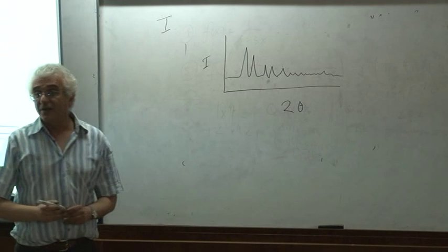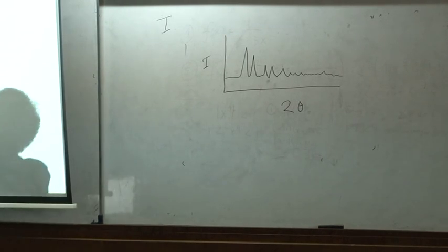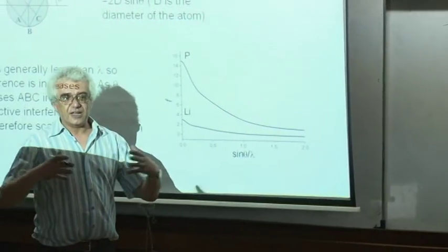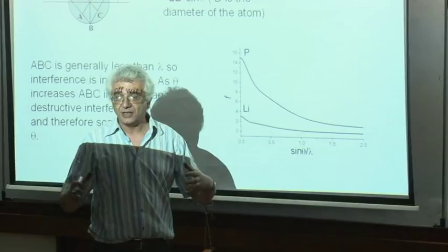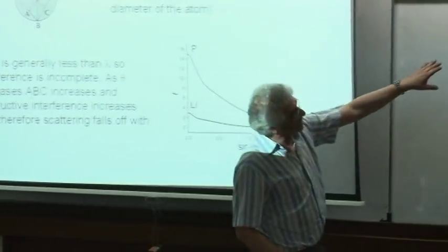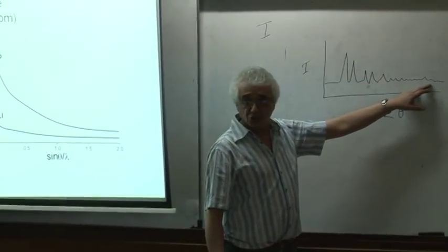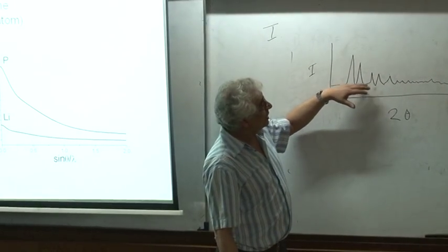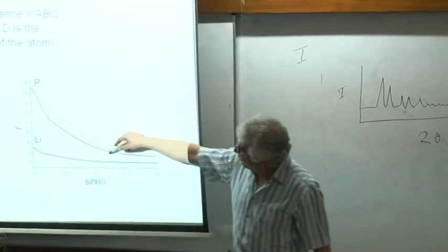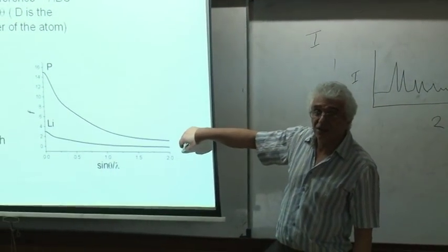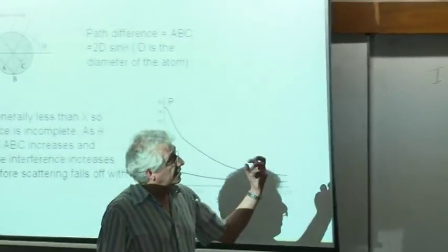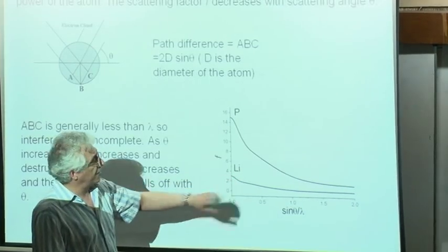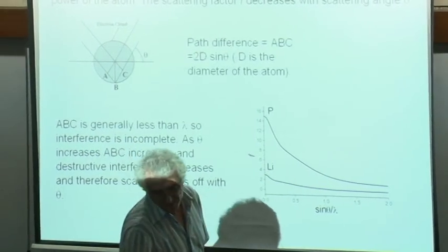That's because your scattering is falling off like this. If you combine that with the fact that the atoms look a bit bigger when they're vibrating, you see this scattering fall off depending on temperature, because the atoms vibrate more at higher temperature, and this destructive interference increases. So that's the visual manifestation of this fall off in scattering.